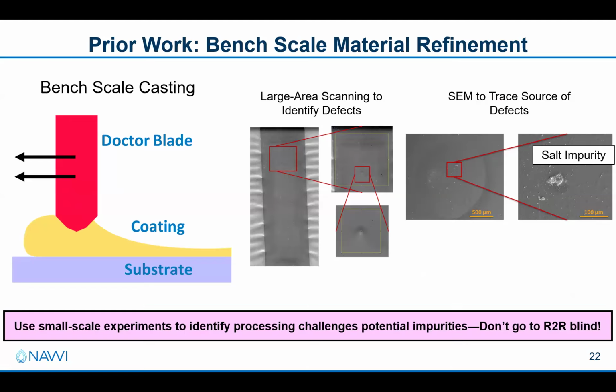bench scale material refinement. Whenever we're working with a new material, there are almost always some initial challenges encountered when trying to scale it up to the roll-to-roll system that just aren't obvious based on common bench scale fabrication practices. As an example, for membrane casting, it's very common to cast membranes from polymer solutions onto glass plates. That's the convention. Glass plates have a very different surface energy than most of the plastic substrates that people tend to coat onto for actual high throughput roll processing. And as a result, you tend to get different kinds of fluid dynamic instabilities related to how the material will wet out the substrate.